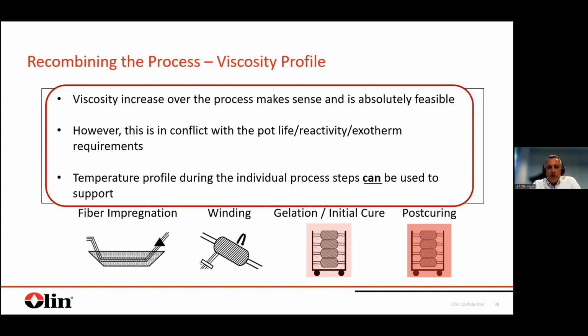However, there are still some conflicts, and this is, for example, in the resin bath, you want to have low reactivity, low exotherm, long pot life, low viscosity, and at the same time, right in the next step, which is just a couple of seconds away in the process, you expect a very steep viscosity increase, and all this also at low exotherm. So there's a little bit of conflicting parameters in this step, and in the end, these conflicts need to be managed by choosing a proper temperature profile during the individual process steps. And I'll come back to the temperature profile on one of the next slides.